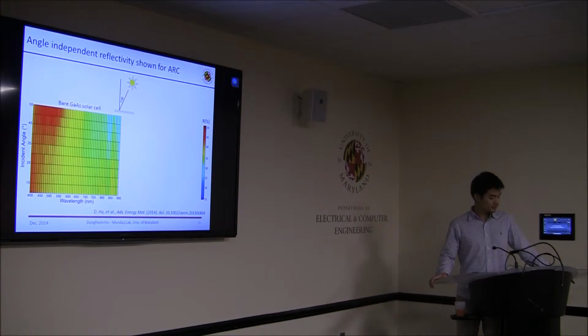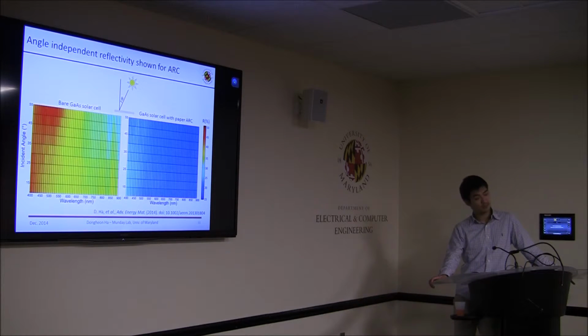So we actually applied this paper on our solar cells, which are planar gallium arsenide. The left contour plot shows the measured reflectivity to air from the bare gallium arsenide, as a function of wavelength and angle of incidence, and throughout the whole data, it is even greater than 30%. However, when we apply our transparent paper, the measured reflectivity has been reduced to around 20%. The other thing we can see here is that even if we change the incident angle, it is around the same, which means that we have angle-independent behavior with our new ARC. That is because, as I told you before, this transparent paper has large scattering, which made our solar cell have really angle-independent behavior.